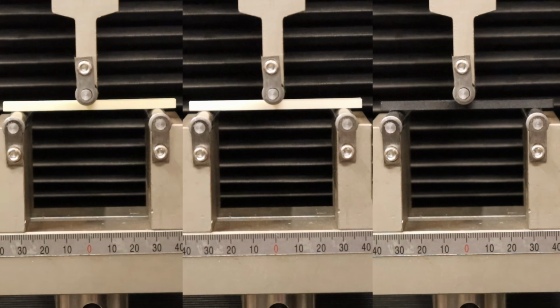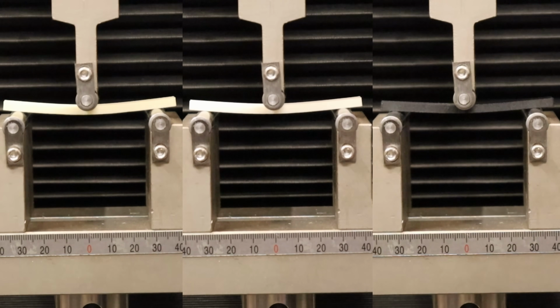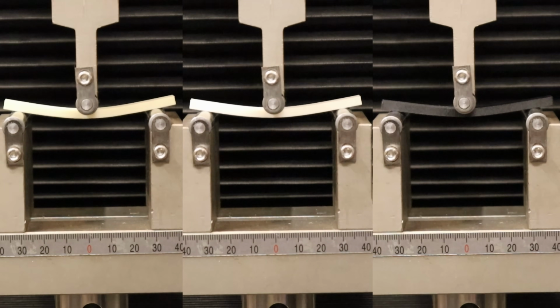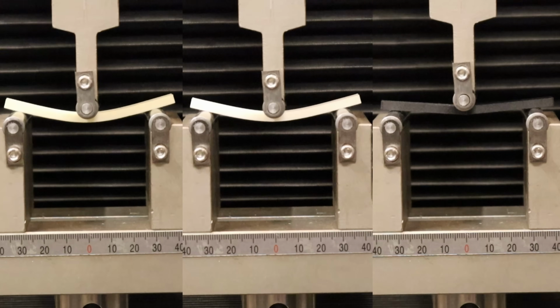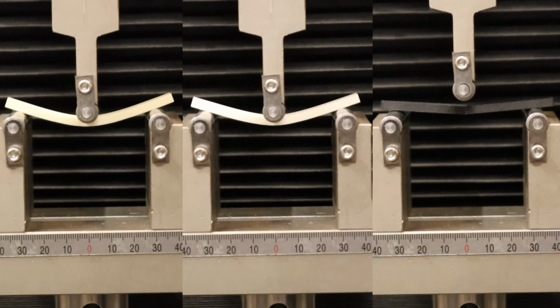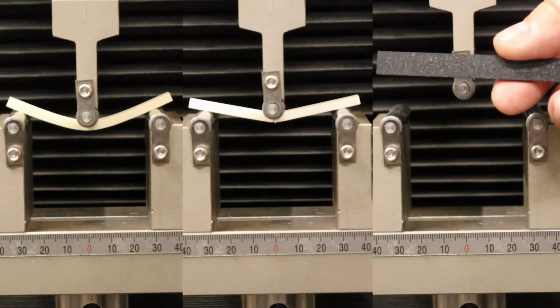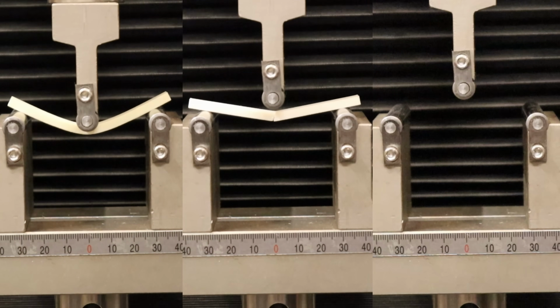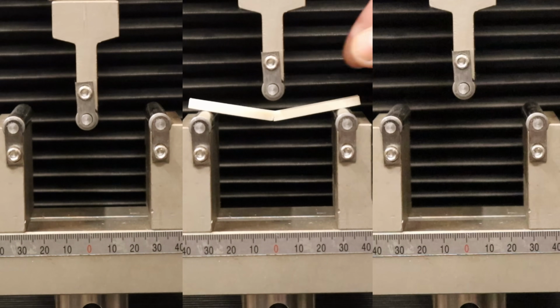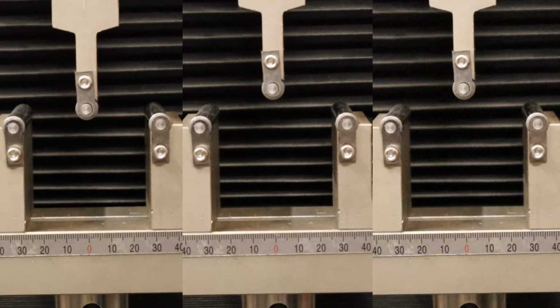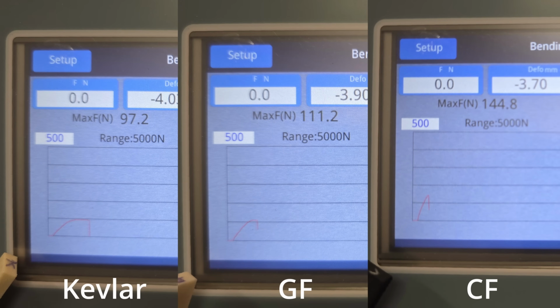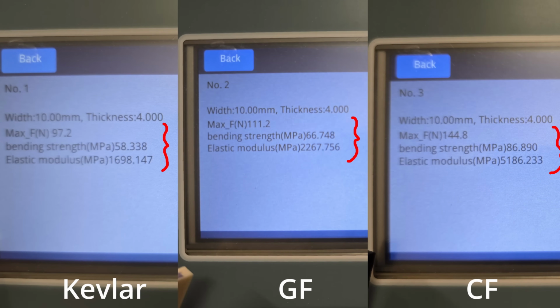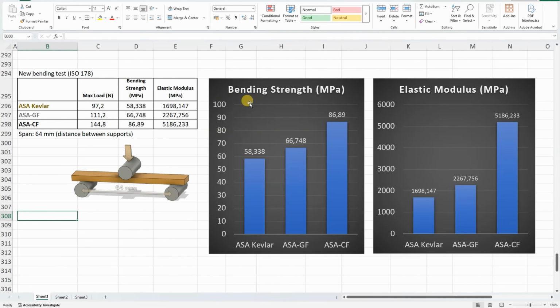And then my second bending test on the universal testing machine. The distance between supports is 64 mm. And not only the maximal load, but also the behavior is different between these three materials. The machine stopped the testing when it reached 50% of the maximum load, or after the break, like in the case of Kevlar. 3 graphs side by side: maximal load, bending strength and elastic modulus. Well, if you watch the bending strength and elastic modulus, the carbon fiber version is the strongest, especially here. Very minimal deformation under maximal load.